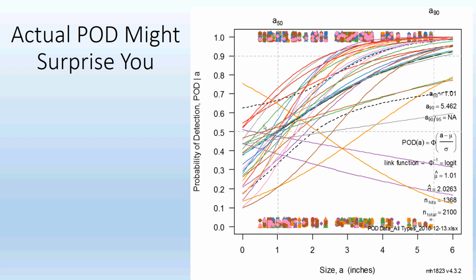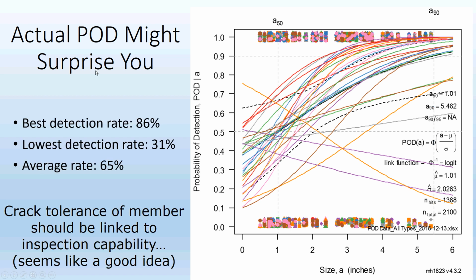But you see some other funny things here, like notice the three individuals for whom the detection actually gets worse with crack length. Well, that's kind of concerning, isn't it? And you look at that data, and it turns out that one of the things that became apparent is it's the more seasoned inspectors. And generally, we have this view, well, let's send Fred out because Fred's been doing this for 30 years. Fred is good. Well, that's no guarantee of performance, right? Just because someone has done it a long time, there's no guarantee that if someone finds small cracks, that they find all the small cracks. If I go down to, say, the half-inch crack size, well, in the thick of the data, maybe there's a 30% chance we'll find that. But there's also a high probability we'll miss it.